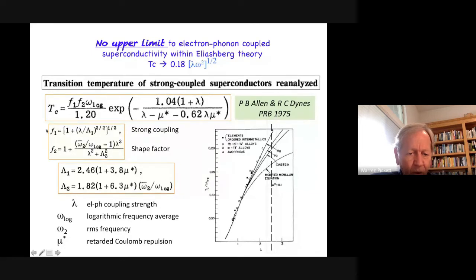And these two factors out here take into account, one is a strong coupling correction, because without that, this doesn't behave right as lambda gets large. And the other one is a shape correction. So if you have a very simple phonon density of states, this will just be one. But if you have a more complicated one that's spread out, bimodal, something like that, this gives you a shape correction, how it influences TC in the Eliashberg equation.